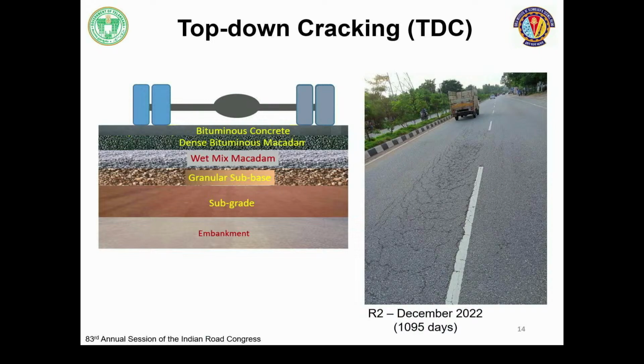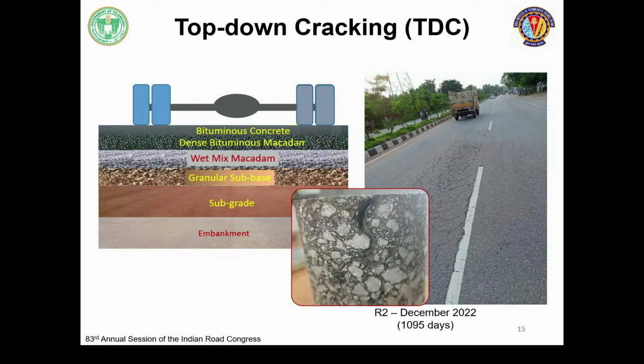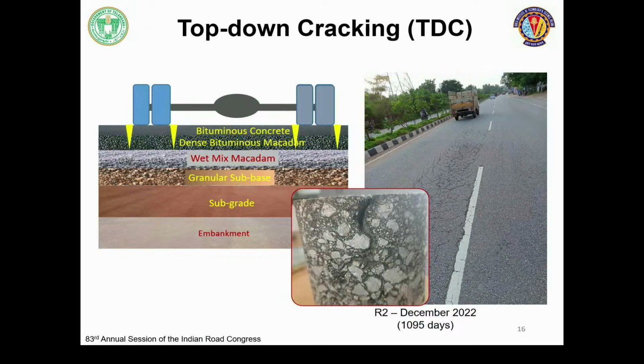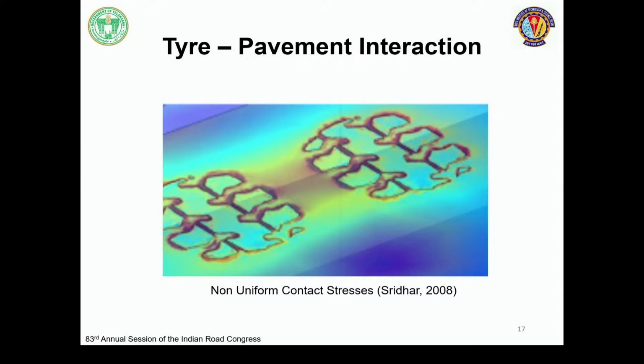After some time, 3 years down the line, we predicted that it may crack. And when we went and observed, there was cracking. But the cracking was not the routine bottom-up cracking. It was from the top, which is relatively new, though it was my PhD topic at Kharagpur. But even today, it is a new topic. The cracking starts from the surface and comes to the middle, maybe the top 20 to 25 mm is what is critical, and then if it is ignored, it goes to full depth. So at 25 mm, they try to mill and do some patching. Though it was not along all the wheel path, in some locations wherever the air voids were quite high, what we observed was the surface cracking or top-down cracking. We call it in short TDC.